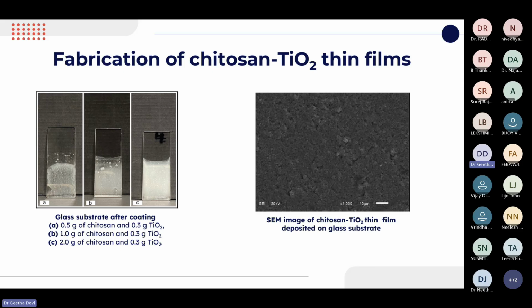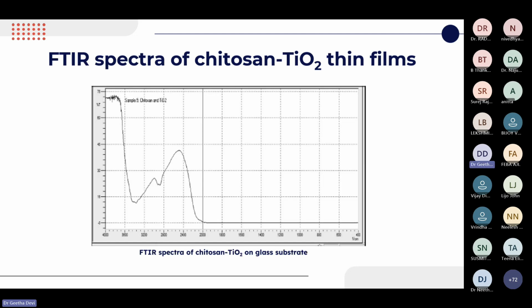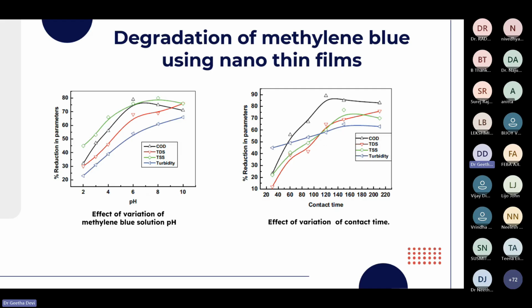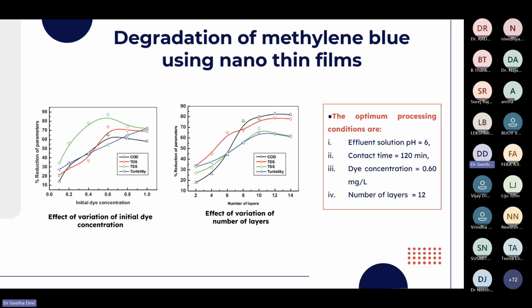We characterized it using scanning electron microscopy, and it is seen that the particles and also the polymer were coated uniformly, completely covering the surface of the glass plate. This is the FTIR spectra of the chitosan titanium dioxide thin films, and these are the degradation results of the nano thin films, varying the number of layers, also pH, contact time, initial dye concentration, and the deposition layers.